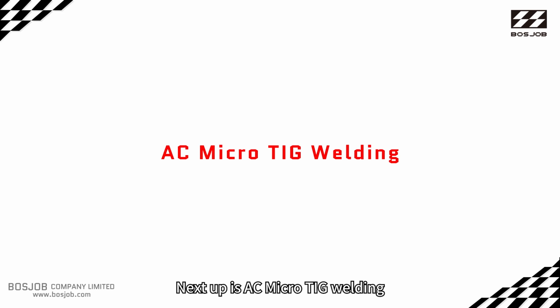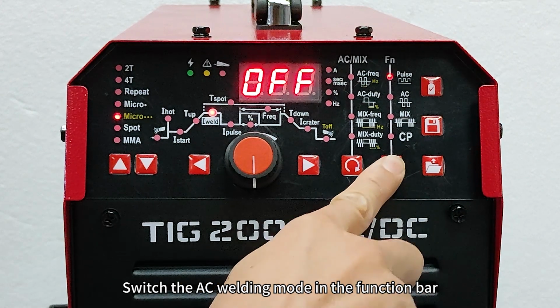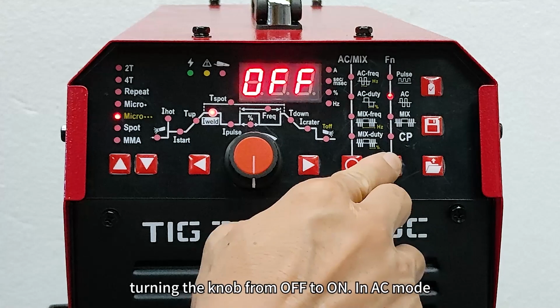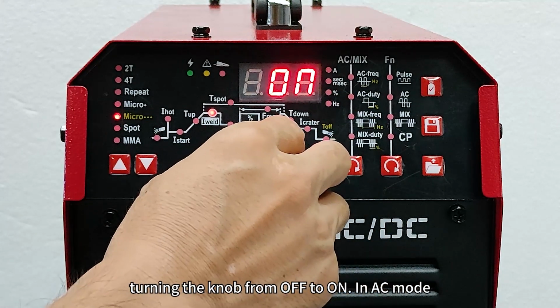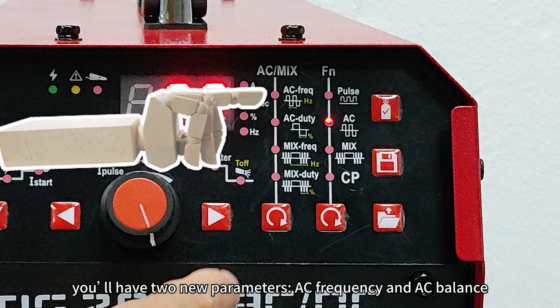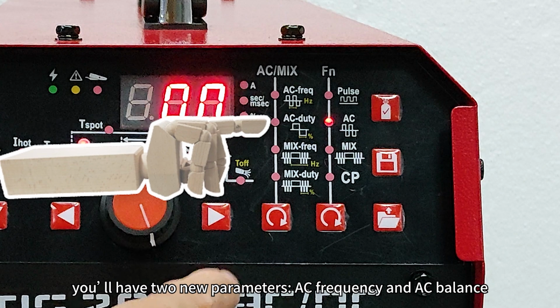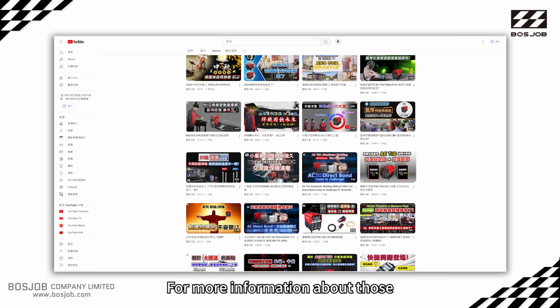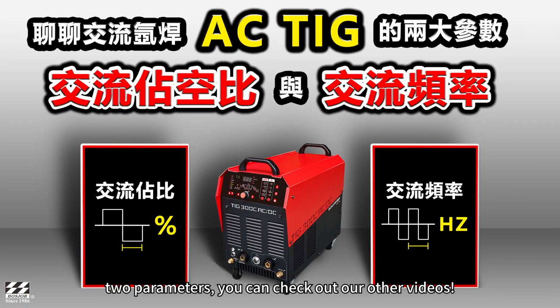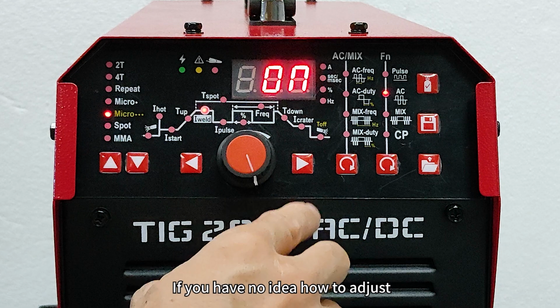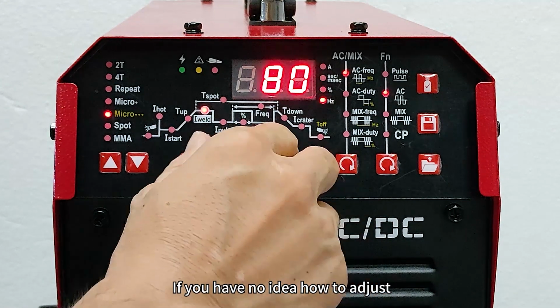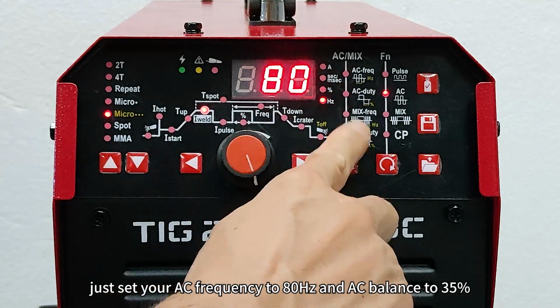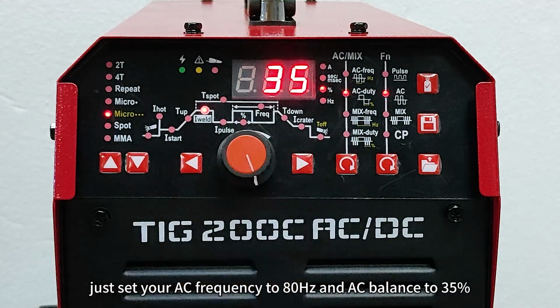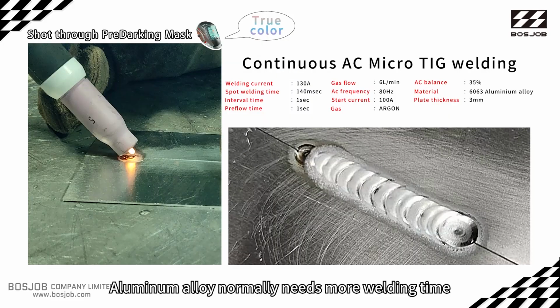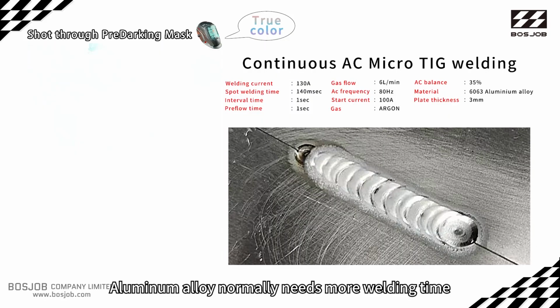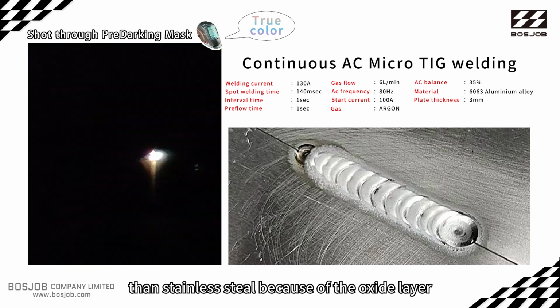Next up is AC Micro TIG welding. Switch the AC welding mode in the function bar, turning the knob from off to on. In AC mode, you will have 2 new parameters, AC frequency and AC balance. For more information about those 2 parameters, you can check out our other videos. If you have no idea how to adjust, just set your AC frequency to 80 Hz and AC balance to 35%. Aluminum alloy normally needs more welding time than stainless steel because of the oxide layer.